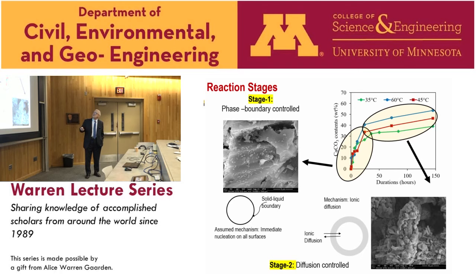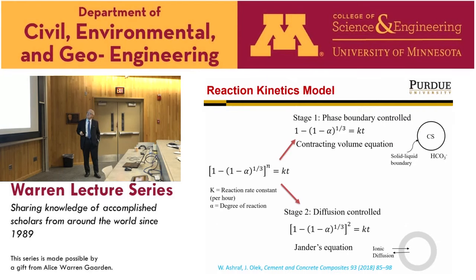So we have stage 1, phase boundary control, and we have stage 2, that is diffusion control. Because now when you form this barrier here, CO2 has to go through it, and it has difficulty going. Diffusion process is a slow process. We are not able to achieve more than about 50% of carbonation, which means about 50% of the grains originally present are actually not carbonating. We are working right now on trying to improve the efficiency of this process.